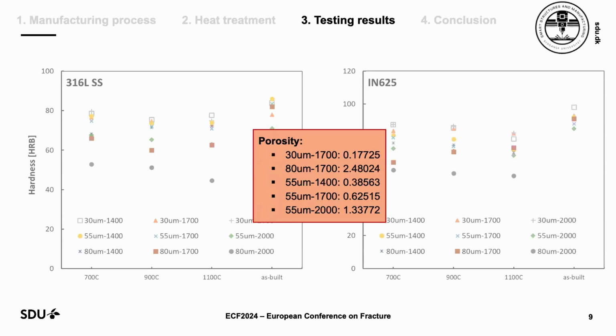And when we increase the scanning speed while keeping layer thickness constant, again, the porosity level increases as well. So, again, this is exactly what defines energy density. Increasing scanning speed or increasing layer thickness decreases energy density. And if we have a decrease in energy density, it means that we are not going to have uniform melting of the material, right? And that's the case. If you have a higher layer thickness, it means that for the same energy density, we are not going to have remelting of the sublayers and better bonding between two layers, right? So that's the reason why we have less UTS or strength for the materials with a higher scanning speed and layer thickness.